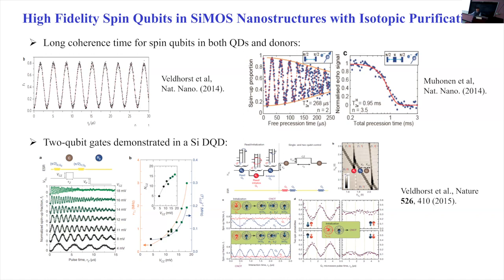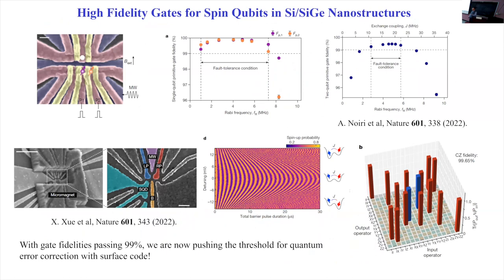Okay, and those were from 2014-15 in silicon MOS. And in just this past year, there have been several experiments in mostly silicon germanium type samples. So the active layer is still silicon, but the barrier, instead of oxide, is now replaced with silicon germanium. People have demonstrated single spin qubit gate fidelity on the order of 99.9%, and two-qubit gate fidelity of 99.5%. So you look at the titles of those papers, they are saying, well, we're at the threshold where we can implement the surface code to do quantum error correction already.